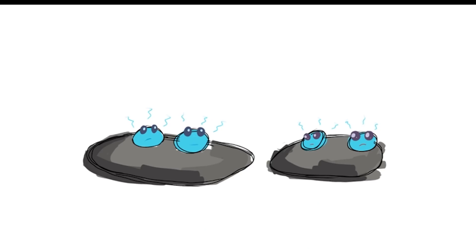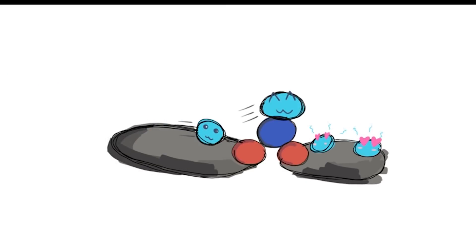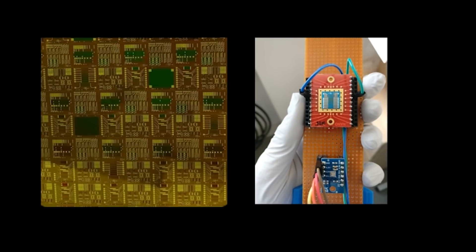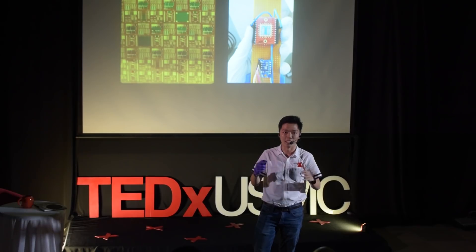The theory behind this is simple. In a nanocrystalline system, you do not have a straight crystal — instead, you have islands of crystal which are very conductive. In a very conductive system, you have electrons trying to go over, but they do not have enough energy to get across. When an oxidizing gas, for example NO2 — nitrogen dioxide, which is one of the pollutants in the air — is absorbed onto this crystal, they provide a bridge. So this electron can now jump over this bridge and get over to meet their girlfriend. This is pretty much how we use this material as an environmental sensor.